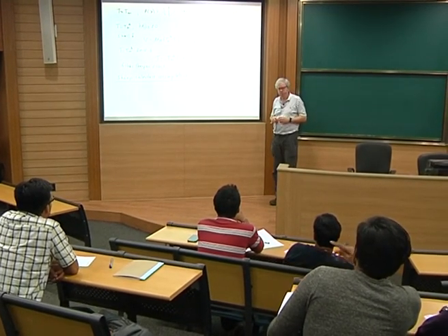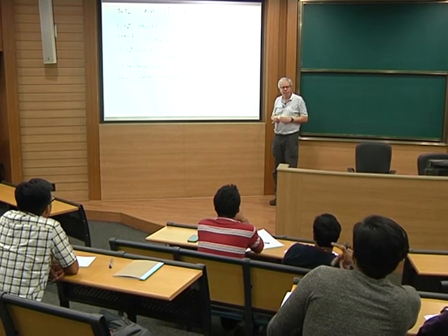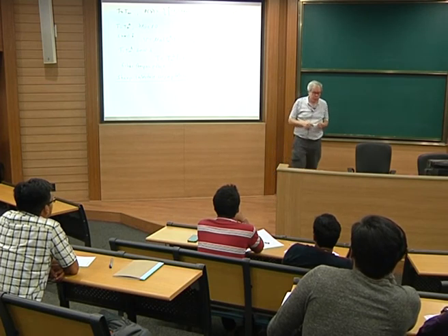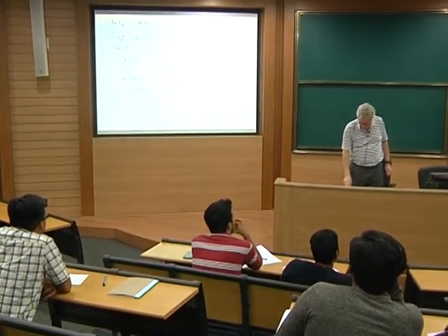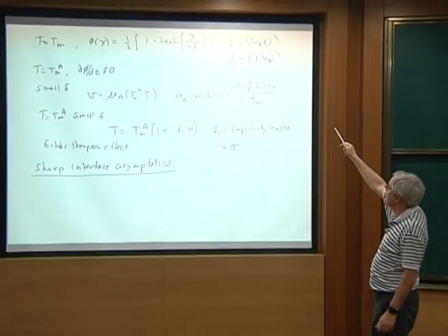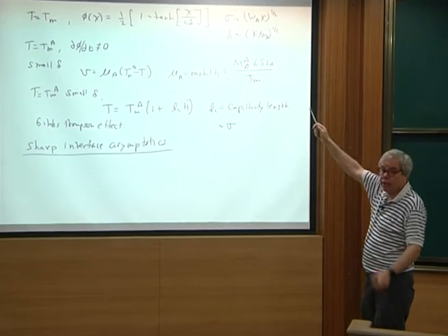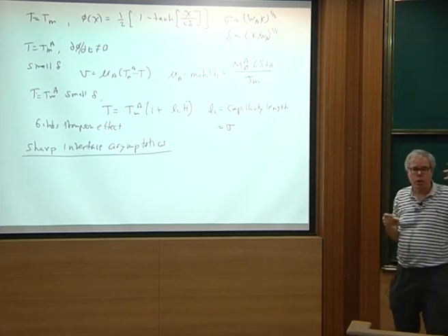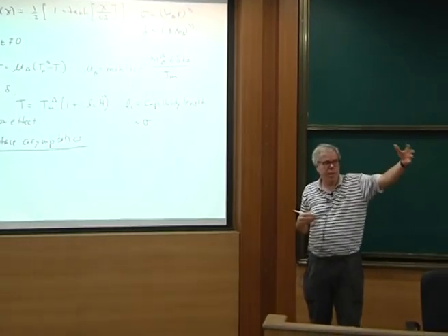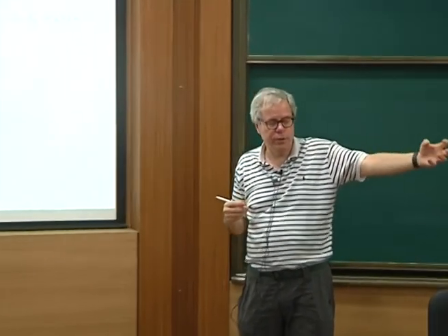Yep. So why do we care about whether the interfacial energy is fixed or not? Why does the KKS model come into the picture? Oh yeah. So the nice thing about the KKS model is that you can fix sigma to be in fact only equal to W_A. It's not a function of any of the bulk free energies. And so if you think about this in terms of a Calphad representation, you have a Calphad database, and then you have these complicated free energy functions. You pull those free energy functions out of the Calphad database, and you can fix the interfacial energy, and it doesn't change.